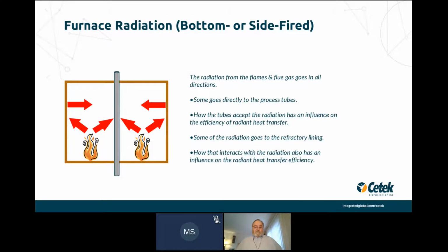Here we are showing a similar schematic, but bottom fired, where you see the flames from the burners. And the radiation obviously goes in all directions. Most of it will go directly to the tubes. Some of it will go to the refractory, and then from the refractory surface to the tubes. The high emissivity coating has no effect on the radiation going directly from the flames or the flue gases to the tubes. It only has an effect on that going from the refractory surface to the tubes. So instead of getting a 50% increase in radiant heat flux, we get something like 5%, because the wall has a lesser effect than the direct radiation from the flames and the flue gases.